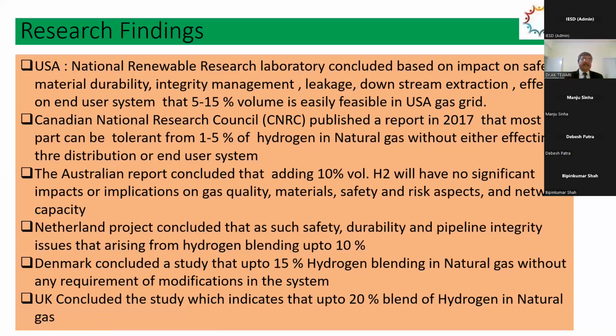So research on hydrogen blending in natural gas has been carried out almost the world over. The US indicates that 5 to 15% by volume is possible, and has given clearance for their USA grid. Canadian research is a little more conservative; the research council, that is a laboratory, undertook the tests, and they indicate 1 to 5%. The Australian report says clearly up to 10%, no problem. And of course, they have tested significant impact on quality, material risk, and other things, and found not much.